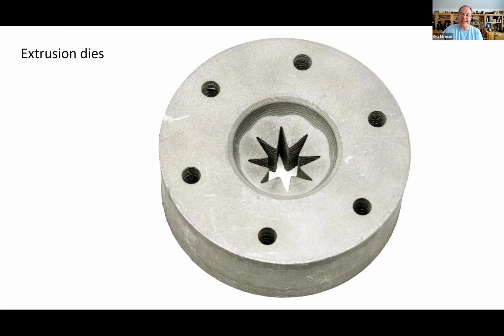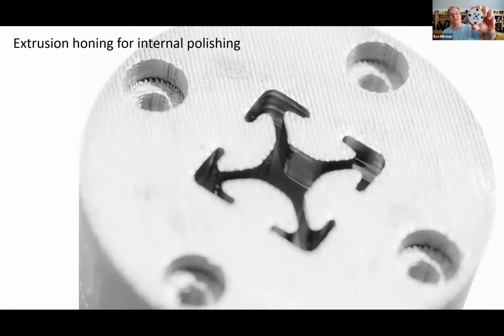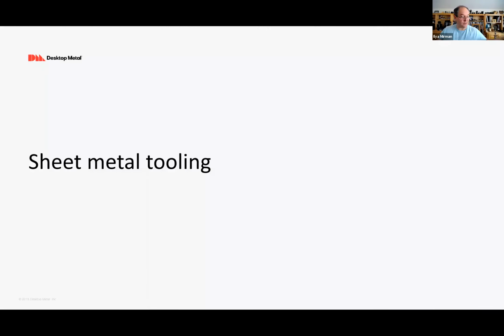So this one you might EDM this shape. Here's an extrusion die with a familiar 80-20 profile. In this photo, you might see that this surface is particularly reflective. You can do, of course, extrusion honing so that whether it's aluminum or zinc that flows through here or plastic, it flows easier. So the same things you might do to dies, you can do to these dies.